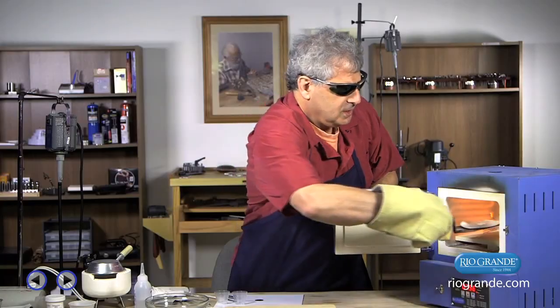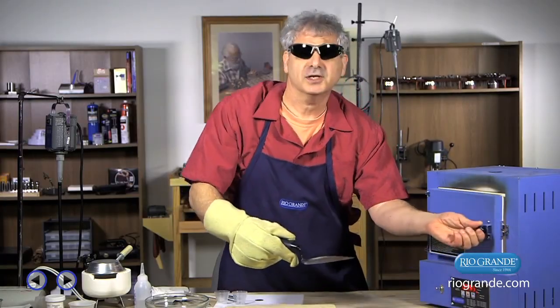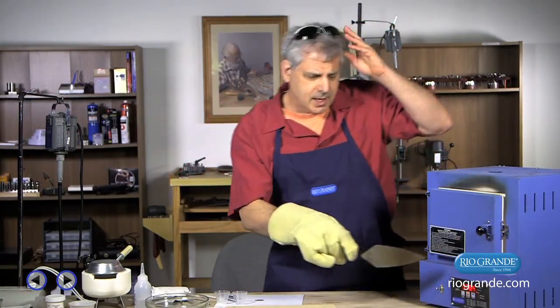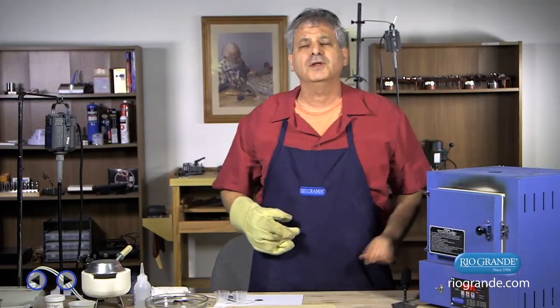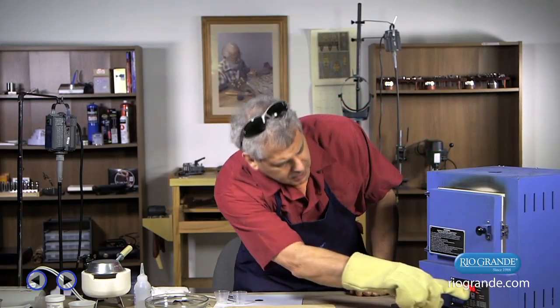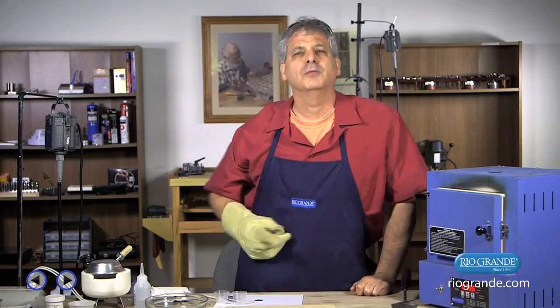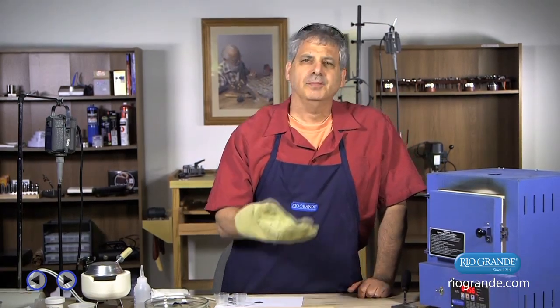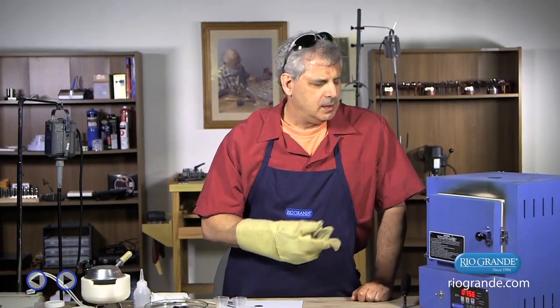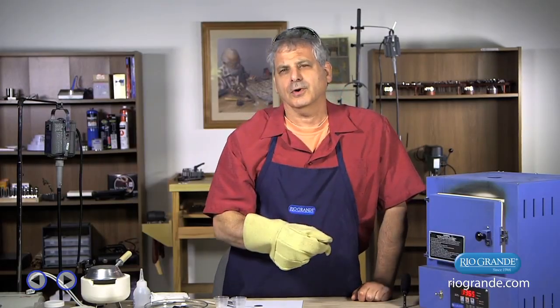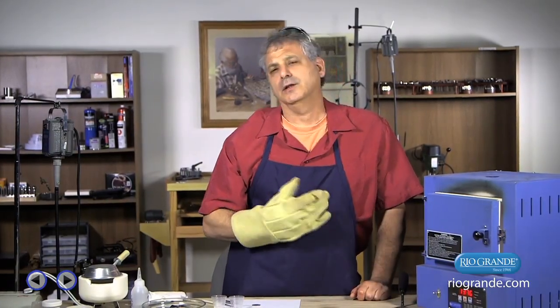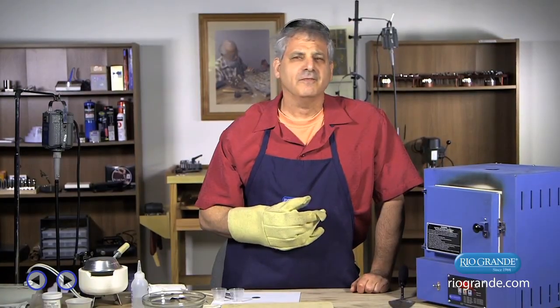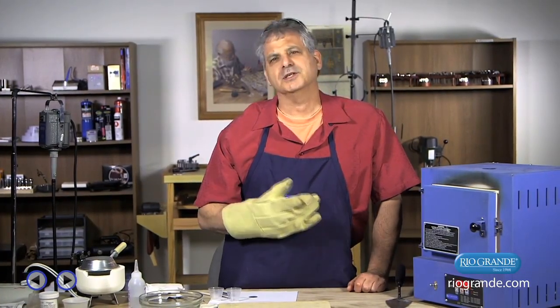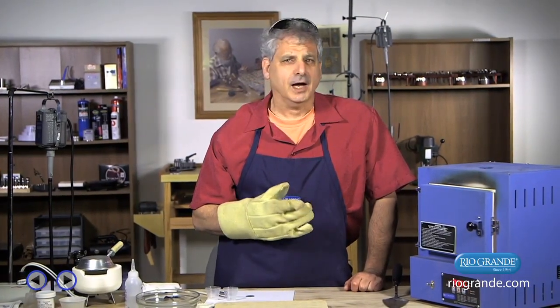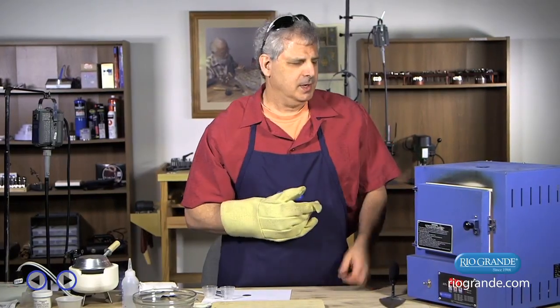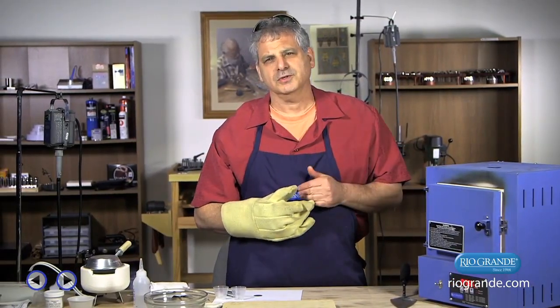And I'm going to put this in here. And generally it's going to take about 1 minute to 2 minutes. And I programmed this kiln for about 1450. As you can see, it's already dropped down almost 100 degrees. So it's going to start building back up. And of course, the longer I open this door, the cooler the kiln got, and the longer it's going to take. So if I'm firing at a lower temperature, it just takes longer. If I'm firing at a higher temperature, it's shorter. Every time I open the door, it cools.